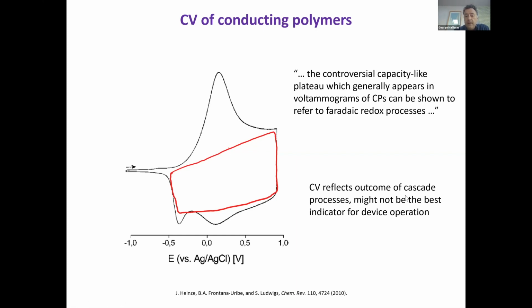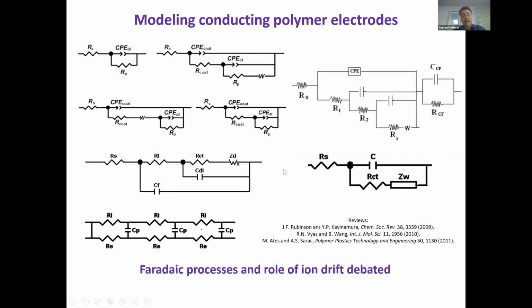My view, which will become clear as we go along, is that cyclic voltammograms are a particularly bad way to study these systems because they reflect the outcome of a cascade of processes. There are too many things that happen here. And what you measure, the current, is an outcome of at least 3 processes. And it's not the best indicator for device operation. You need to break it down a bit more in order to decide whether you have capacitive or Faradaic.